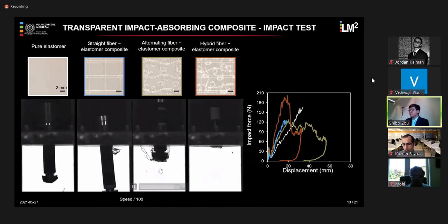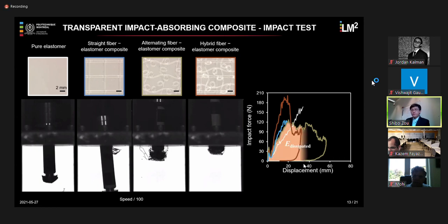And as you can see here, the spring back of the falling dart enabled us to measure this unloading curve on the impact force displacement curve. With this unloading curve, we were able to calculate how much elastic energy is released upon unloading, and how much energy was actually dissipated out of the material during this impact.